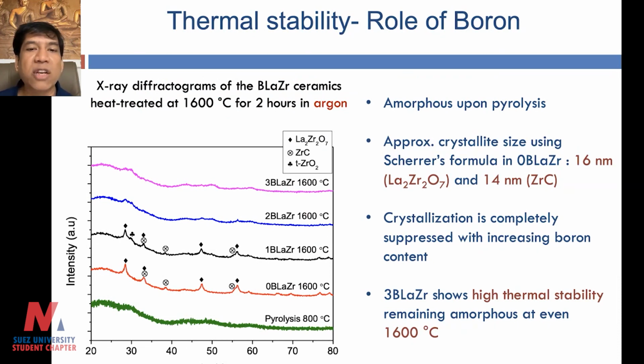And as you can see from the X-ray diffractograms, when we make them, the first thing we do is test their high temperature capability, and you can see that at 1600 degrees Celsius, the ceramic is completely amorphous, which is good for us because we want them to be amorphous. Although it is thermodynamically not very stable, we make these thermodynamically metastable materials as stable as possible so that they can be used for extended duration of time.